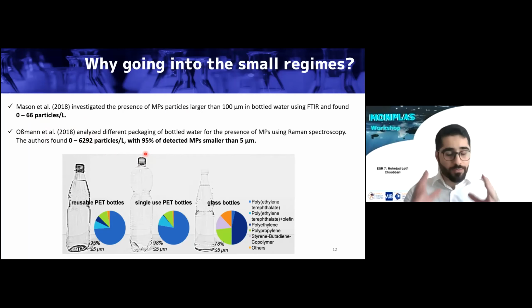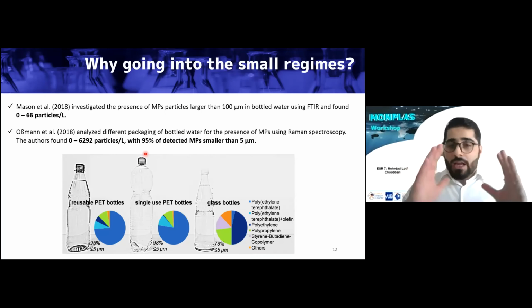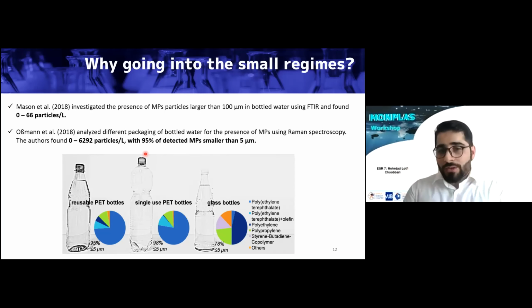Here, actually, I don't want to make a firm conclusion or to say this study was better or this method is better. The point that I want to mention here is just we should consider the sample, and based on the sample, we should go for a proper method for our analysis. And here in this image, you can see the types of the plastic particles found in this work. You can see that surprisingly, they have also found plastic particles in glass bottles with 78%, again, smaller than 5 micron.